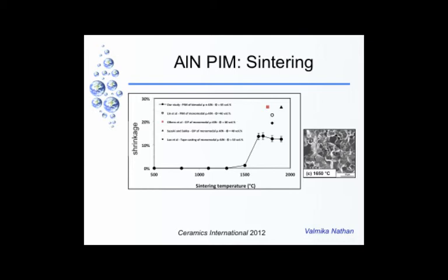So we are sintering at a lower temperature, and we are getting lower shrinkage because of the higher initial volume fraction of powders. What we found was the agglomerates could break down in the twin screw extruder when we mixed it, and that allowed us to get the very high volume fraction. We have to do additional experiments in this region to understand more, but you can see from this microstructure of the fractured surface that it is 99+% dense. There's almost no porosity over there.